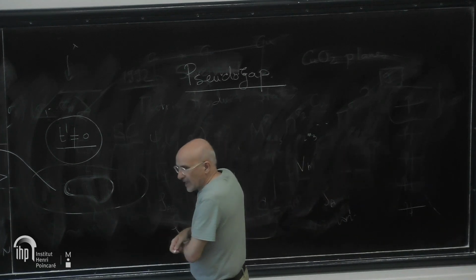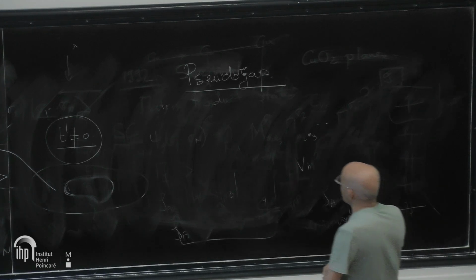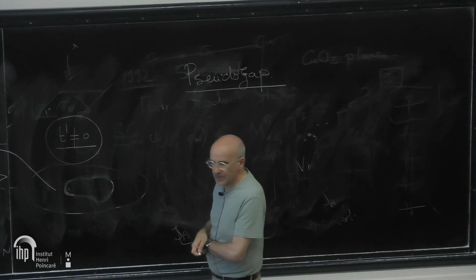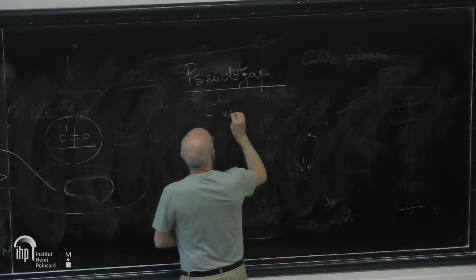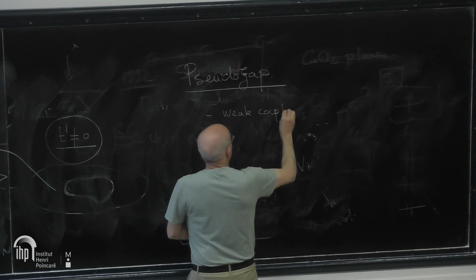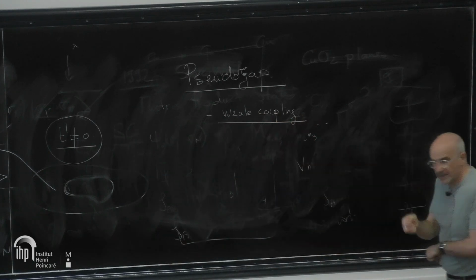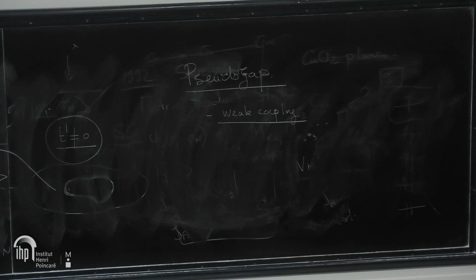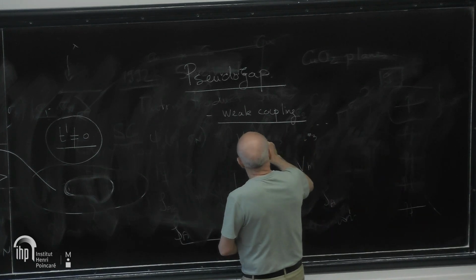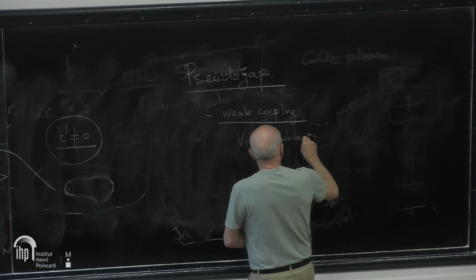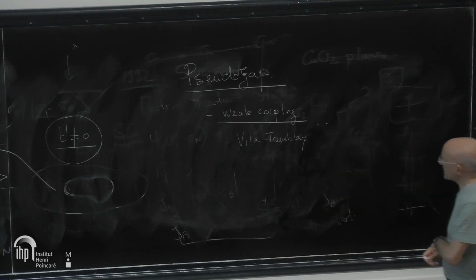Okay. So a combination of quantum embedding DMFT methods and, more recently, finite temperature extensions of DMRG MPS methods have established that the pseudogap is actually associated with short-range antiferromagnetic order at strong coupling. We can keep this for the discussion session where I can explain this in more detail. But in weak coupling, we have a well-established analytical theory of the pseudogap phenomenon, which is due to Vilk and Tremblay, again from the mid-90s. And Nicolas Dupuis contributed also to this back in the day.